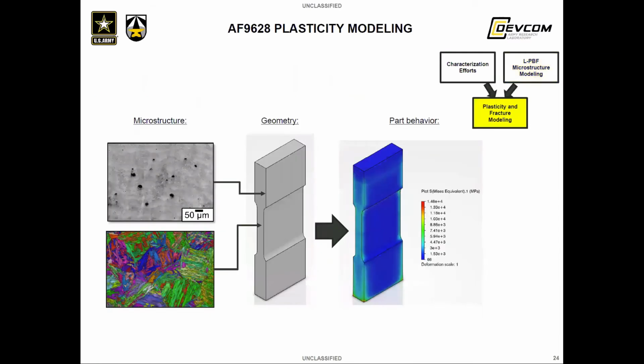Shown here is just a very basic schematic of the mapping from microstructure to geometry to part behavior. It's important to note here that there's an intermediate effect of geometry in the mapping from structure to part behavior. The laser powder bed fusion process is very sensitive to geometry due to the effect that geometry has on cooling. And so optimizing the shape and orientation of the part being printed is also an essential part of the design process for additively manufactured parts.